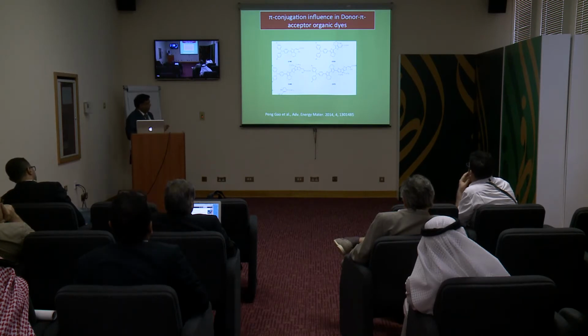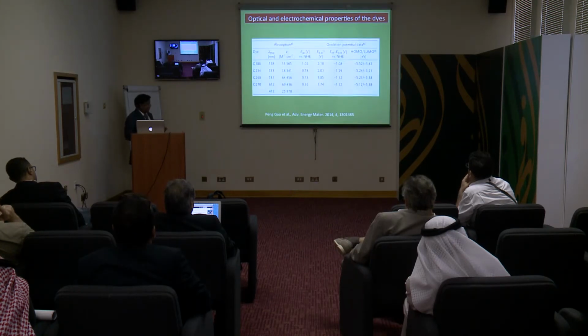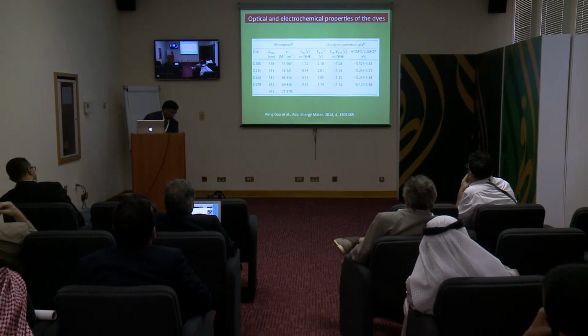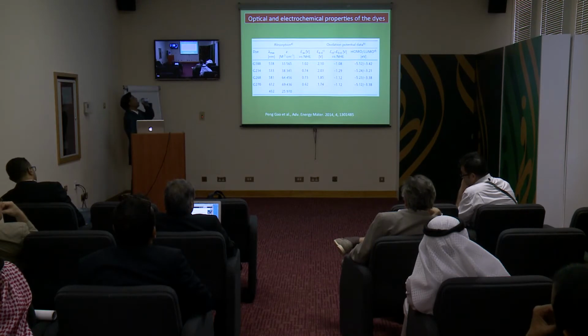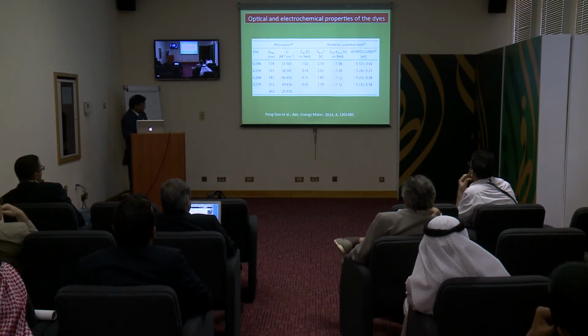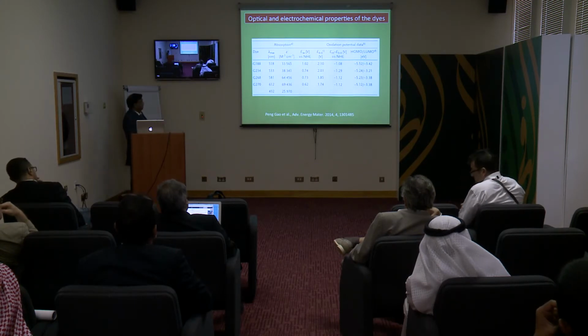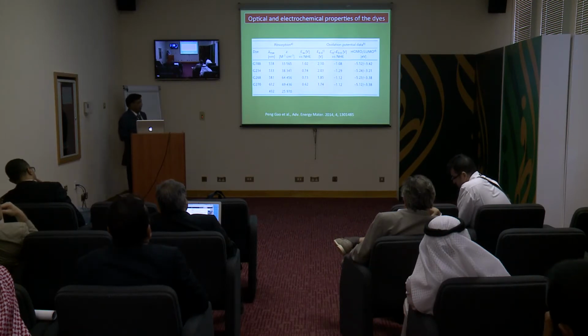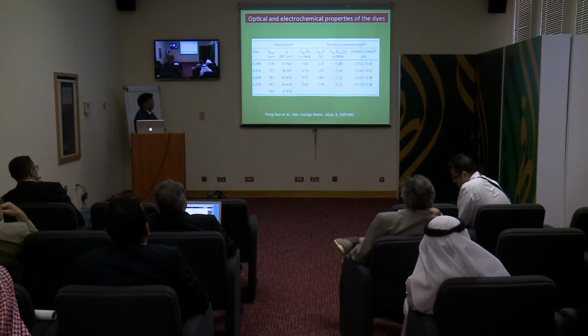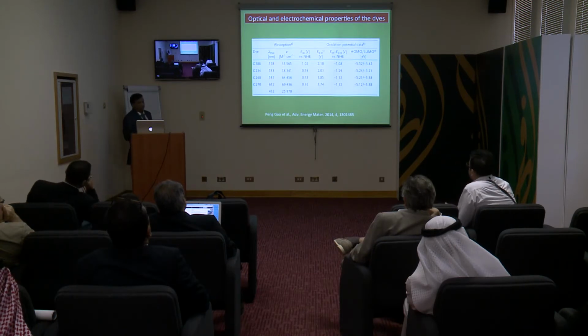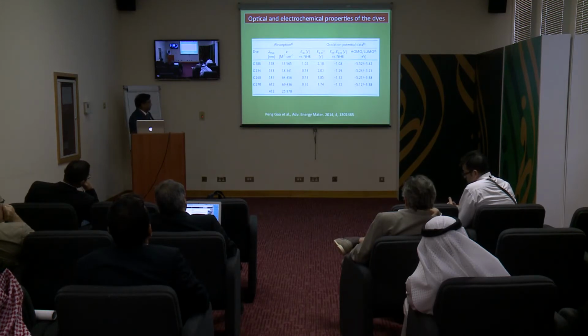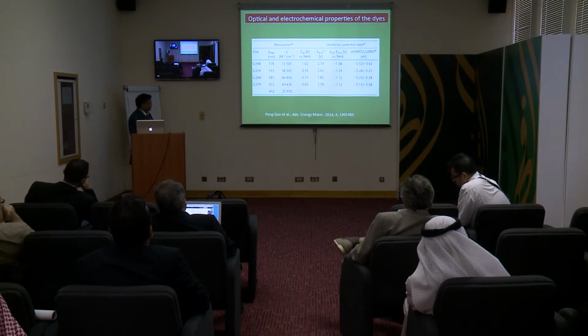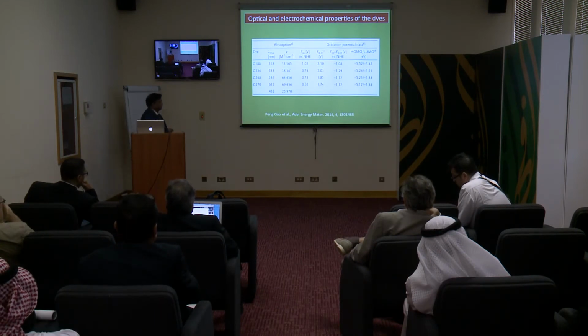To understand this, the electrochemical properties are measured and tabulated here. Here you can see that we have different absorption spectra. With only one EDOT molecule, you can see here it's 518 nanometers. By adding one more EDOT, it is shifted by 15 nanometers to the red, which is 533. But instead of another EDOT, if you substitute with a CPDT molecule, the absorption spectrum moves from 518 to 581. There is a huge shift because the CPDT has more pi conjugation than EDOT here. But if you take 2 EDOT molecules and then put the CPDT there, it is further shifted to 612 nanometers. So this shows how one can tune the spectral response from 518 to 612 nanometers.